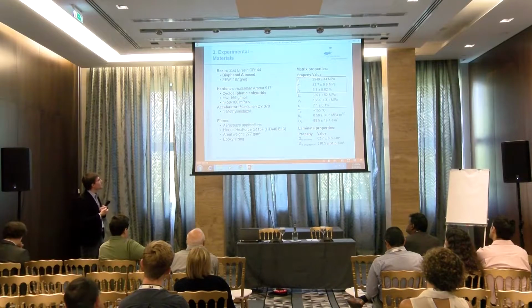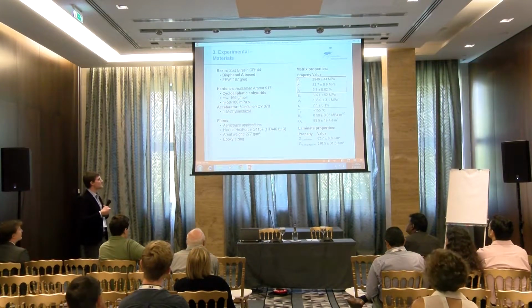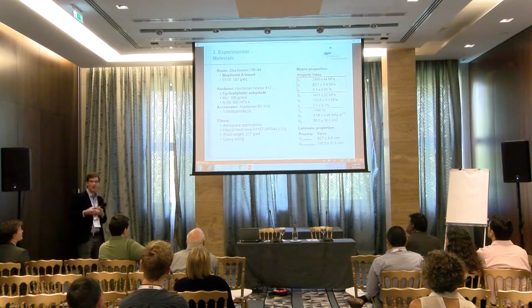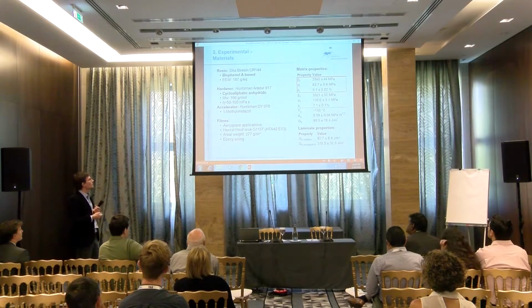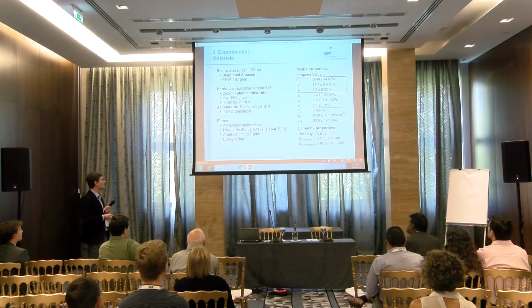The base material I used was a bisphenol A-based resin with a cycloaliphatic anhydride. That's especially good for having a longer pot life, to think about filament winding and so on. So no snap curing here. We used aerospace-certified fibers. In that case, it was a Tenax fiber.